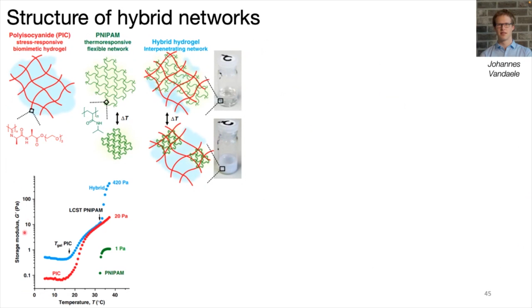So here you see the stiffness of the material once you increase the temperature. If you have the PIC only, here it is basically a liquid. Here it starts the gelation of the PIC, so it starts forming a gel. And then, as you increase the temperature, it just increases the stiffness a little bit. Oh, sorry, here. No, the red one, yes. The polyNIPAM, you see, collapses at around 32 degrees, the polyNIPAM that we are using. So above 32 degrees, the stiffness increases. And when you mix the two systems, you have the PIC gelation, fine. And once you have the collapse of the polyNIPAM, it also increases the stiffness.